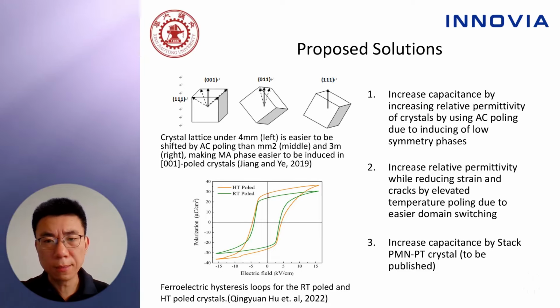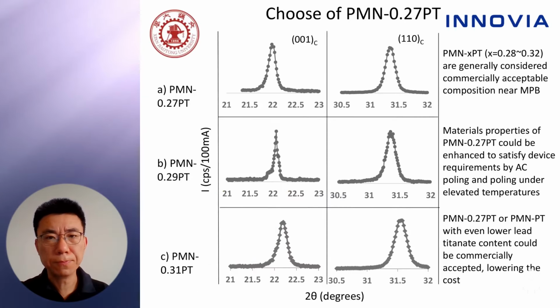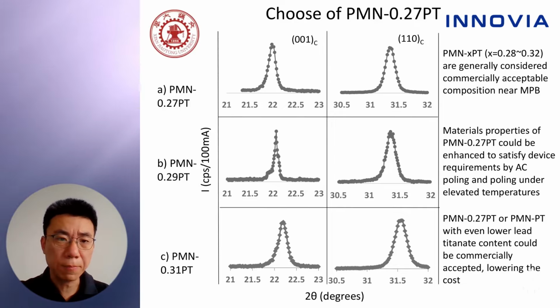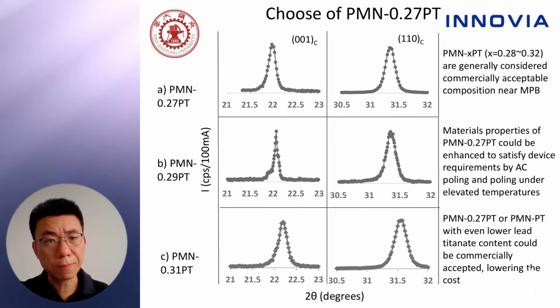Thirdly, we propose increasing capacitance by stacking of PMN-PT crystals. This is still under research and will be published soon. Why are we choosing PMN 27% PT? The graph on the left shows the X-ray diffraction pattern of two typical peaks, 001 and 110 peaks, of three compositions, PMN 27% PT, 29% PT, and 31% PT. 27% PT is what we are experimenting with.